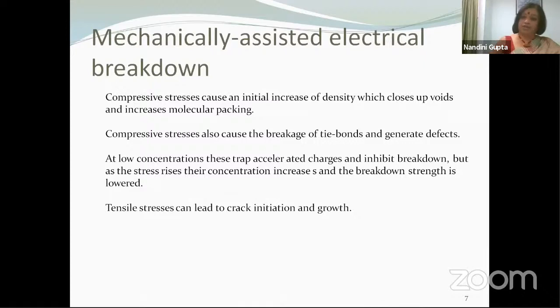So when defects are formed, there would be charges accumulated, and these charges will cause the breakdown strength to be lowered. Essentially, it is not the breakdown strength which is lowered, but because you have a second electric field aiding the applied electric field, you are able to apply lower electric fields before breakdown happens, because within the material, the dielectric breakdown strength is seen much earlier. So this is one situation where mechanical stresses can lead to electrical breakdown due to formation of defects, accumulation of trapped charges, and trapped charges exerting their own electric field over and above the applied electric field.